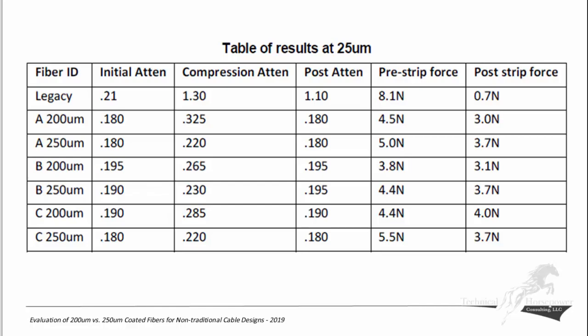The interesting part, and this is where we were quite satisfied with our choice of the strip force test, showed a pretty consistent drop of coatings on the 200 and 250. Slightly more on 200, but not statistically a large difference. And because we only did 3 of each, it wasn't a large enough population for us to get a standard deviation. But these are the averages of those 3. And there were no significant differences between the 3 samples.